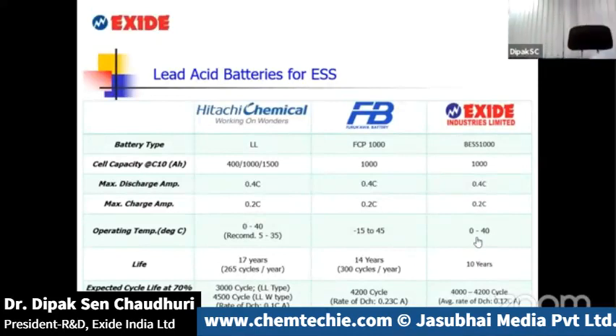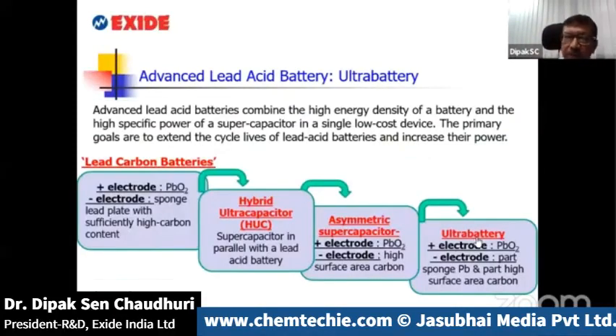Some of the major versions which are available in the global market are the ones which are marketed by Hitachi as well as by Furukawa. Exide, we have also developed this high cycle life, long life energy storage batteries in the lead acid configuration. We are being modest. We are talking of a service life of 10 years and a cycle life which might go up to 4,000 to 4,200 cycles at 70% depth, which is as close as you can get to lead acid, to lithium.